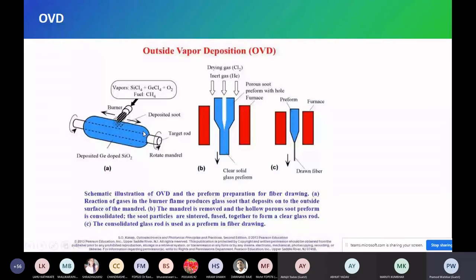So what we do initially is that we take the mandrel, and above that we deposit some layers at a low temperature. It is not very high temperature. It is something around 1500 degrees Celsius. So 1500 is not sufficient for SiCl4, SiO2 to make the glass. It needs very high temperature, more than 1700 degrees Celsius. So at lower temperature, what is going to form? This ash type thing. Okay, we have seen ash. Similarly soot forms, yellow, white color. So we have soot here. This becomes soot, white soot.